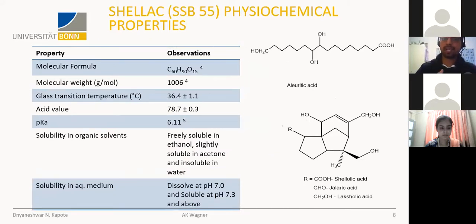And shellac is a well-known excipient in India because it is very common in Asian countries, especially in India. Shellac is not a single excipient, but a complex mixture of organic acids containing aleuritic acid, shellolic acid, jalaric acid, laccijalaric acid. The molecular weight is 1006, with a low glass transition temperature of 36.4 degrees Celsius, making it quite an interesting candidate for hot melt extrusion. It is freely soluble in ethanol, slightly soluble in acetone, and completely insoluble in water because it is pH dependent soluble.